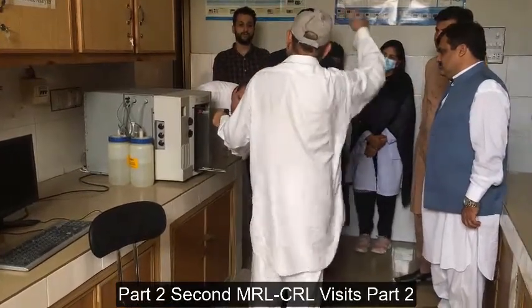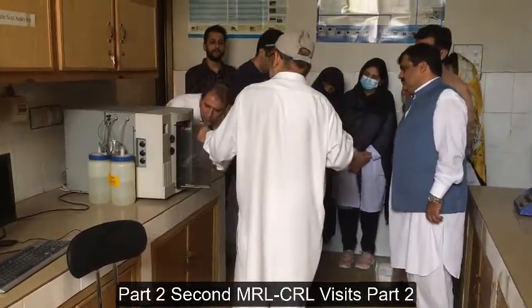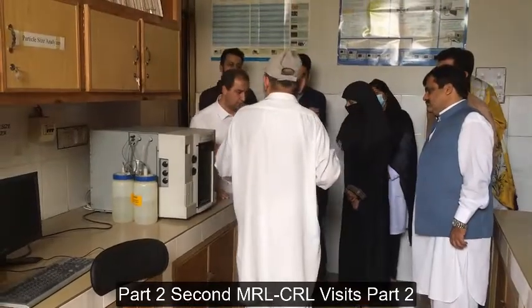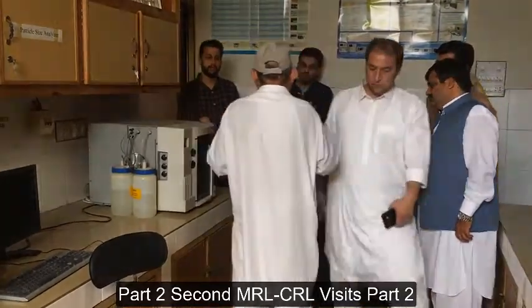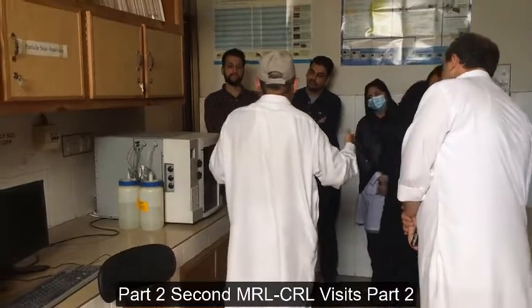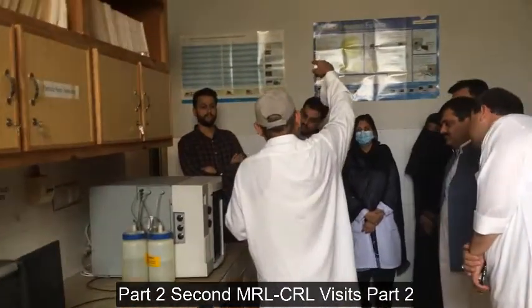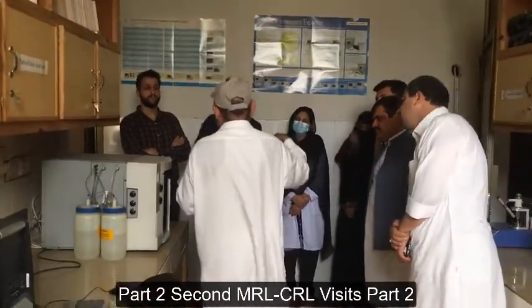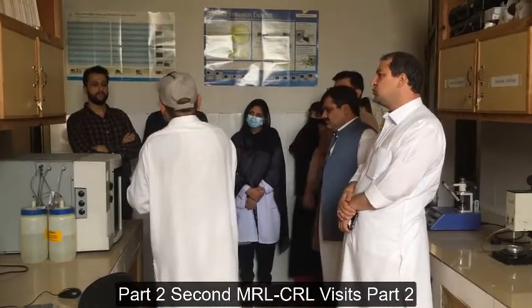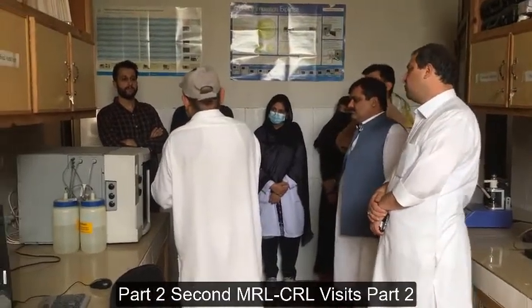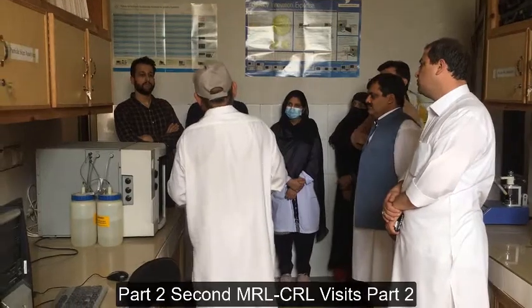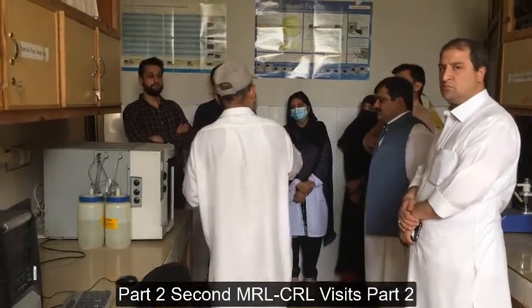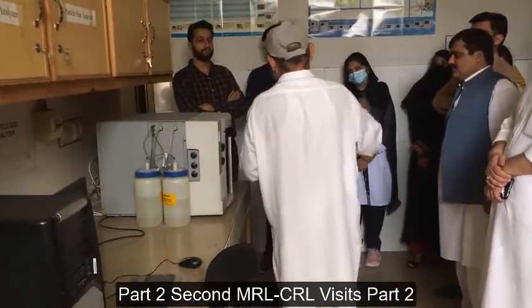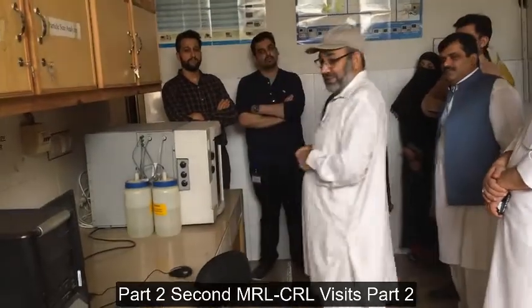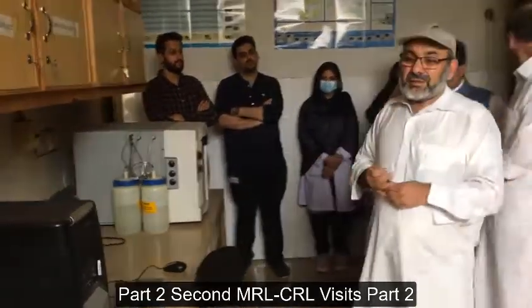It gives us a Poisson type distribution as well. For example, if the distribution is uniform from 1 micron to 3 micron, the maximum number is at 1.5 micron, so it is a Poisson type. If you want to know the exact number of how many particles are of which size, then it gives you a table of that as well. 10,000 particles are of this size, 5,000 of this size, so it gives you those details of the particle distribution.